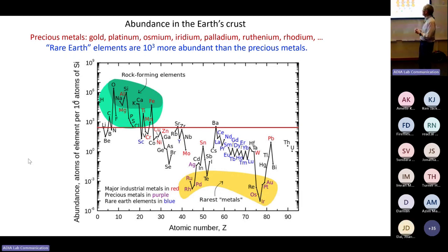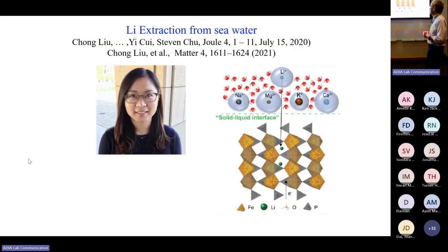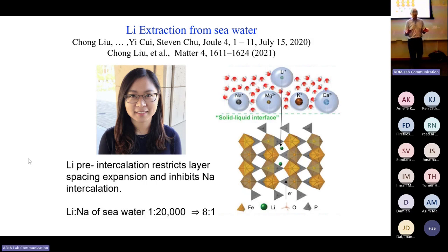When Chong Liu was a postdoc in my group and also a graduate student in Stanford, she's now an assistant professor at the University of Chicago, she began to develop methods of taking lithium in aqueous solution, water solution, and putting them into a cheap battery material. This is iron phosphate. And so the lithium atoms were intercalated between these planes of iron phosphate. And you can arrange it so the lithium ions would go into the battery material and would exclude sodium atoms to a high degree. And her latest results, that she did when she was at the University of Chicago, she can start with seawater at 20,000 to 1 ratio, and she can get 8 times as much lithium as sodium on 1 round trip. So that's perfect, except for one thing.